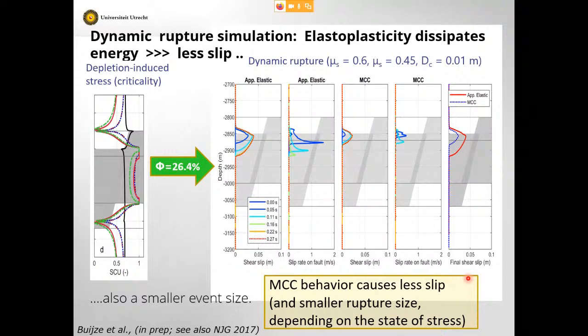We also have put that model into fault rupture models. I don't have time to go into this in detail, but essentially, besides influencing the compaction behavior of the reservoir, the slip behavior on faults when they are reactivated is also influenced, of course, by the behavior of the reservoir. And what you see here is that if you were to assume the reservoir is elastic, you get this slip patch. This is a measure of the final shear displacement on a fault. Here's a fault schematically shown. When you actually take into account the real constitutive behavior of the reservoir, you get a smaller slip patch with less displacement. So it influences the earthquake generation behavior, if you like.